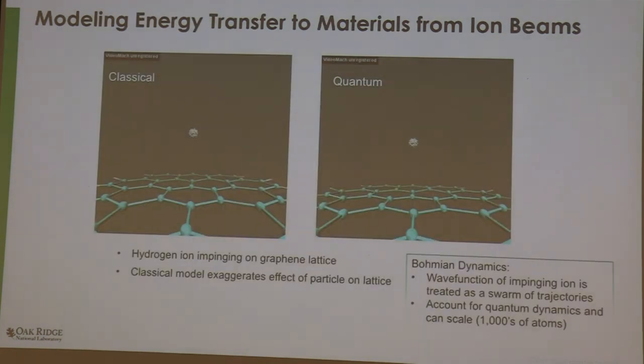Let's see. So this is an example of looking at basically a mimic of an ion microscope. Right? So we have really pretty cool microscopes these days that can resolve atoms at the single atom level, because we focus the electron or the ion beam down to about an angstrom. And we can see angstrom level details and structure. So the question is, well, if I do that and I bombard, say, graphene, and I want to image the graphene with an ion beam or electron beam in an electron microscope, does it do anything to the material? Of course it does, right? First of all, it passes through, or it's scattered, and you can image it, which is transmission electron microscopy.